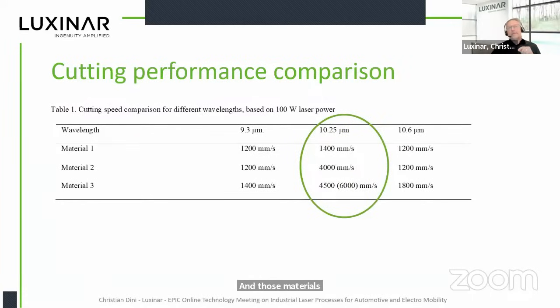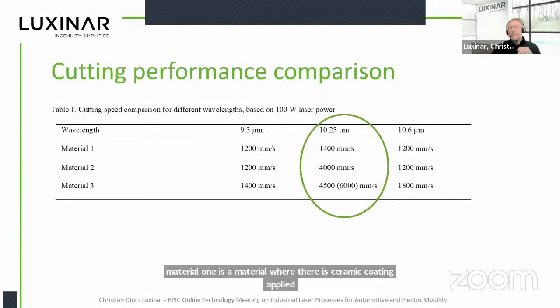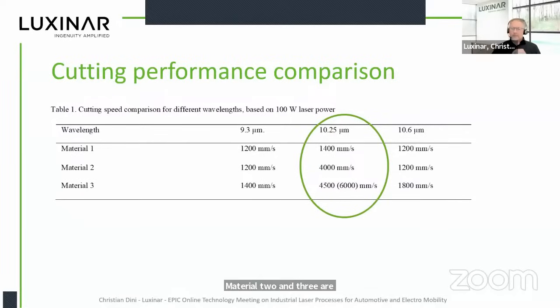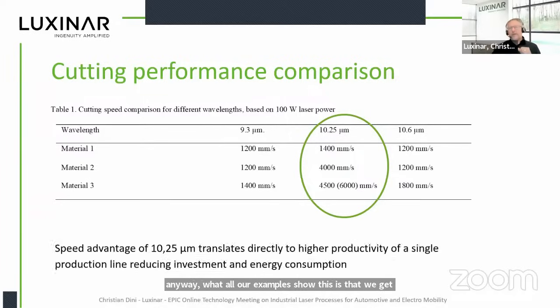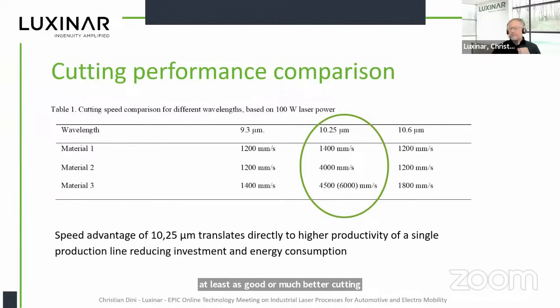Now, a few slides are missing, but this material 1 is a material where there is a ceramic coating applied. Material 2 and 3 are PE foils, but they are not clean PE. There is a slight part of polypropylene present, and that makes it so interesting for the 10.25. But anyway, what all our examples show is that we get at least as good or much better cutting performance with 10.25 microns.